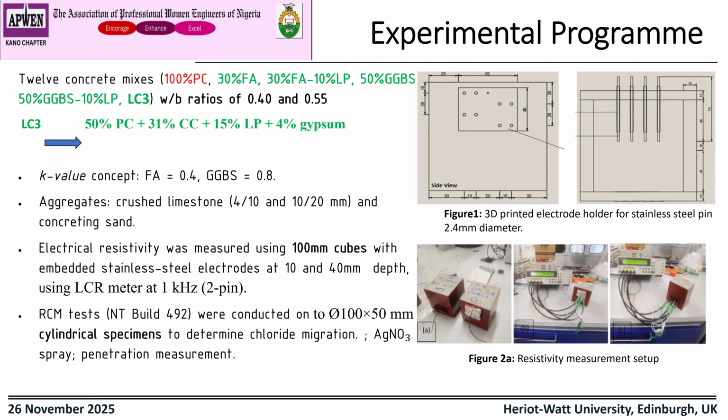2.25, yes. For GGBS it is 0.8, so we have to divide the amount by 0.8. This means multiplying it by just 1.25. That is, adding 25% of the GGBS in the concrete in order to compensate for the hydration product that was removed from the cement. Then we use aggregate, that is crushed limestone, normal gravels that we use in Nigeria and everywhere. So we use millimeter.